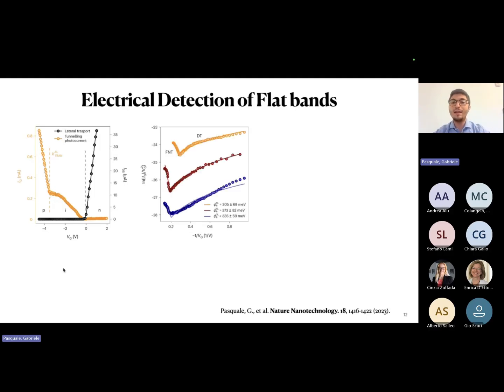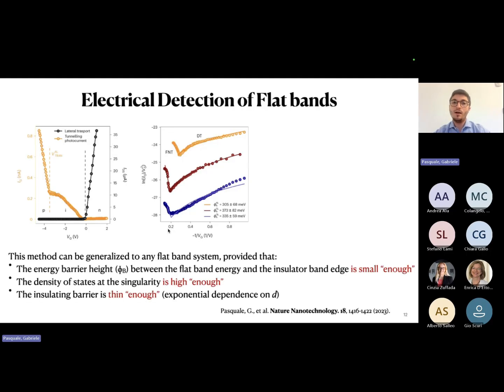We did a full analysis where we show that if you plot this tunneling current in the Simmons scale, you're left with the trend of the tunneling mechanisms. What we see is that there is a sharp change in tunneling mechanism that happens at a specific point, and we went on to demonstrate that this point is exactly the flat band position. So what we have is a method that, with just a quick gate sweep, can locate a flat band in your field effect device.